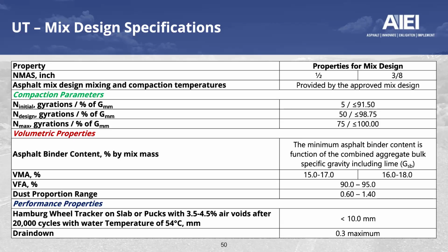Much like we saw in the state of New Jersey, Utah also requires a drain down test on this dense graded mix. Again, that is to ensure that with this rich mix, we don't have an experience of bleeding at those higher temperatures and during production. And again, thus far, we haven't had an issue with any of the mixtures in Utah with that parameter.